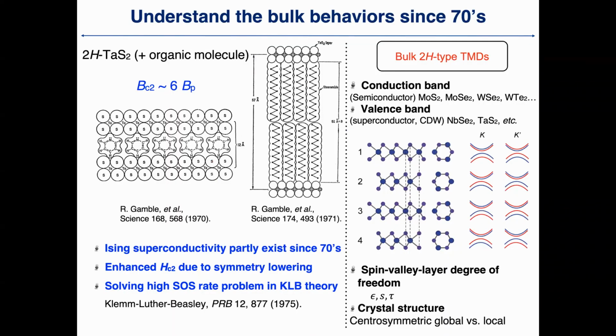And this phenomenon can actually be traced back to some findings in the 70s. At that time, people noticed that if you have tantalum disulfide, which nowadays we know has an Ising type SOC in the valence band, and if you are able to isolate the layers by inserting organic molecules, you start to see an upper critical field like 6 times the Pauli limit. So in the present understanding, this is simply realized by having a system that is more isolated between layers. So if you have a longer chain molecule, then this upper critical field actually goes higher.